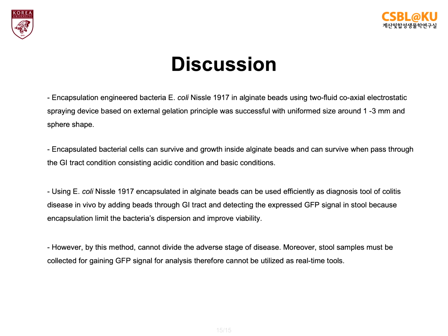Lastly, is the discussion part. First, the encapsulation of engineered bacteria E. coli Nissle 1917 in the alginate beads using a two-fluid coaxial electrostatic spraying device based on the external gelation principle was successful, in a uniform size around 1 to 3 millimeters and spherical shapes.